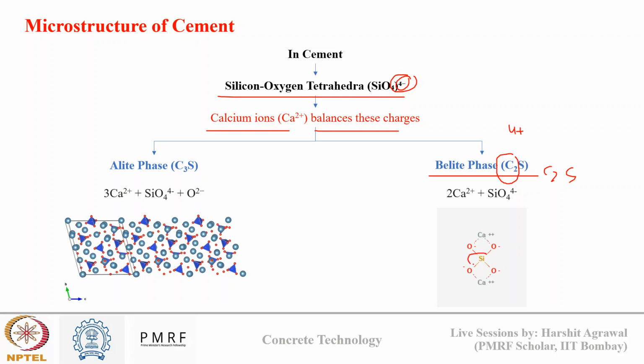Okay, so you can see this is silica, these are four oxygen atoms, four negative charges, two are grouped with calcium, other two are grouped with calcium, and we get C2S. While in alite, there are three calcium ions which give us a +6 charge, and this silica has a -4 charge. And there is an additional -2 coming from the oxygen ion. So that's why we form C3S. There are three calcium ions, there is silica and there is oxygen, so they combine to form C3S.